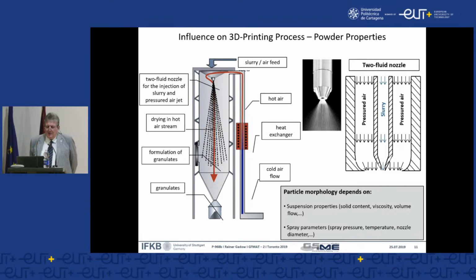And there was some research, including theses in process engineering, to develop two-fluid nozzles, because the spray-dry operation does not only depend on the heat and mass transfer in such a counterflow apparatus, it strongly depends on the type of the sprayed particle in liquid state. So in the center we have the ceramic slurry, the ceramic suspension, and in the outer shell of the nozzle we have compressed air, in some cases also compressed nitrogen, and then the dimension of the nozzle is selected and optimized step by step, so that the particle morphology is obtained as desired.